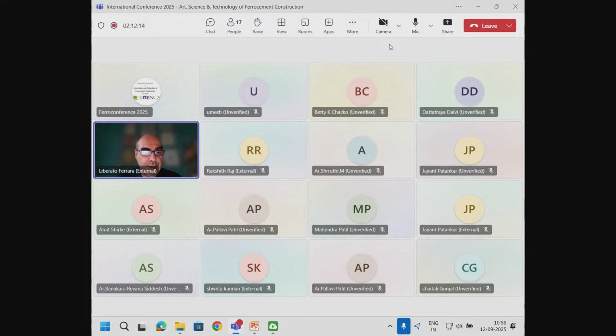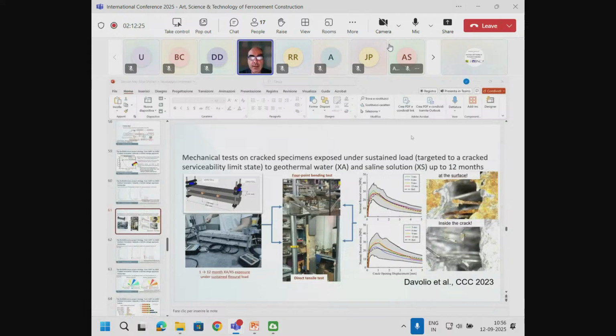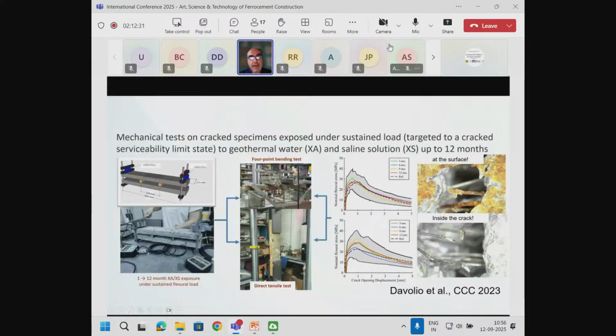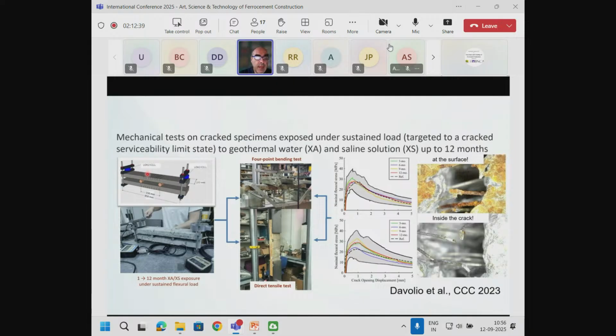Yeah, thank you for the question, because it helps me to point out some issues. I will just reshare the screen. Can you see this slide? Okay. Well, as a matter of fact, this was a test setup that we developed. You see here, these were very thin beams, which were pre-cracked, and then were immersed into salt water in the pre-cracked state and kept under this state, so the deformation was kept constant and so on.